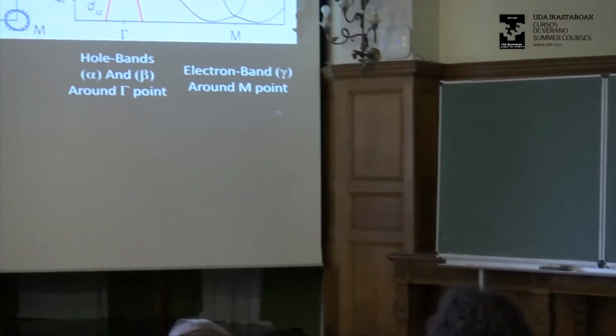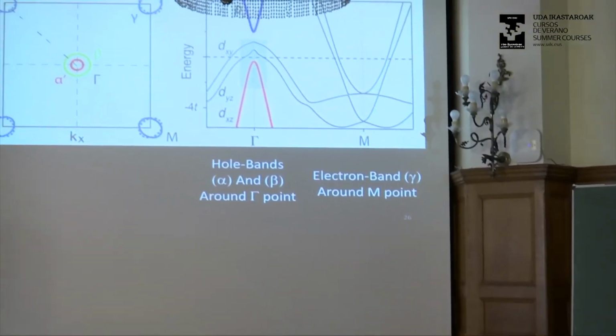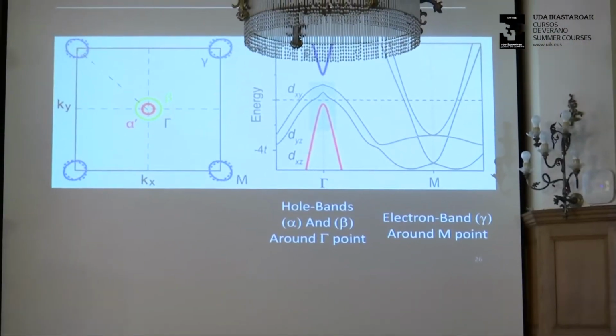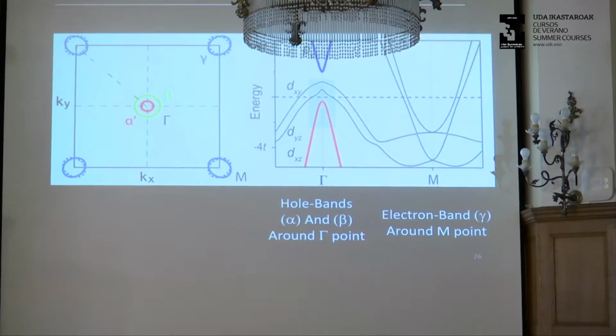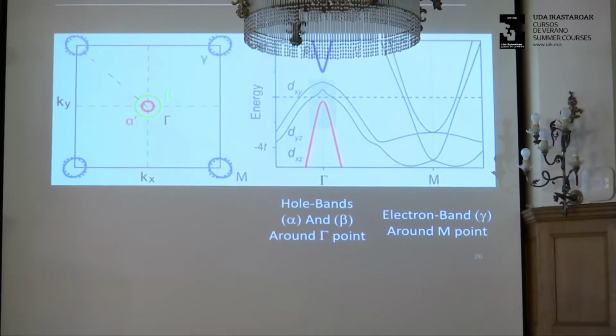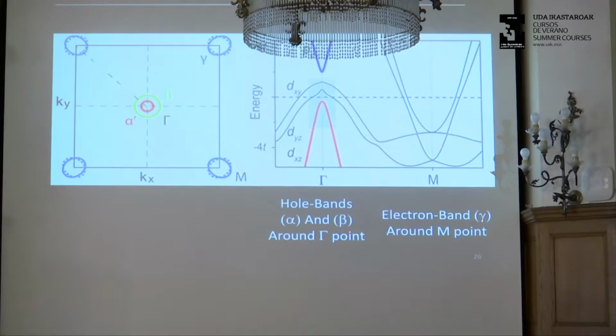This is the band structure of this compound. This is the Fermi surface. You can see there are 1, 2, 3 Fermi surfaces. So these three distinct Fermi surfaces, each of them gets gapped out by superconductivity, and you in fact have three distinct gaps.